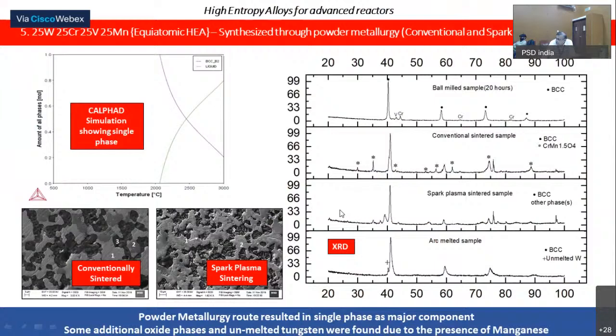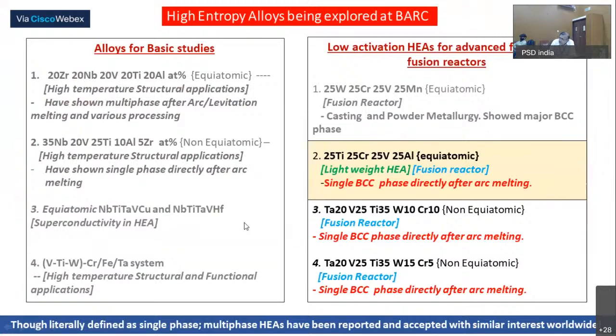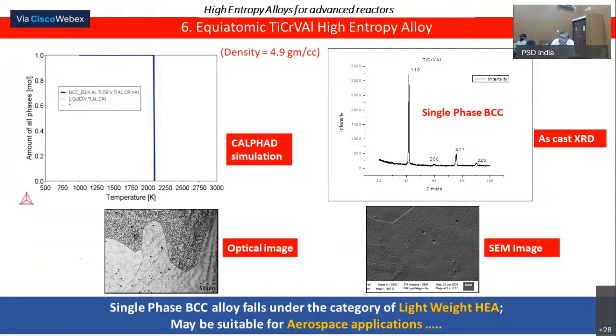And when you do spark plasma sintering, that is, you give a pulsating electric current while sintering, then the region gets welded and you get a very fine structure, and it shows a very fine single phase material. And if I take this study further, after melting, we have identified some of the high entropy alloys, that is titanium, chromium, vanadium alloys, which have a density of 4.9 gram per cc. Let me tell you, titanium has a density of 4.4. So we are very close to a titanium based alloy. Single phase, it has the strength of the titanium alloys, ductility as good as titanium, and this possibly can find an application in aerospace.